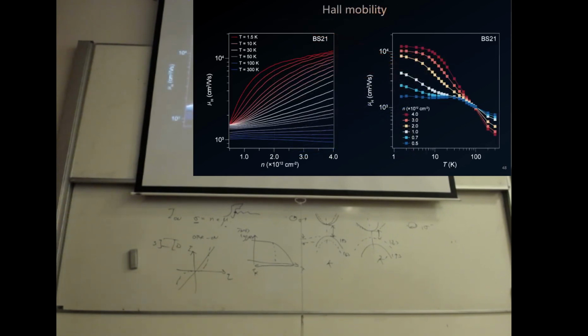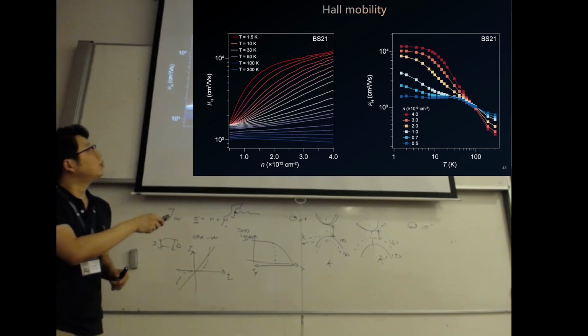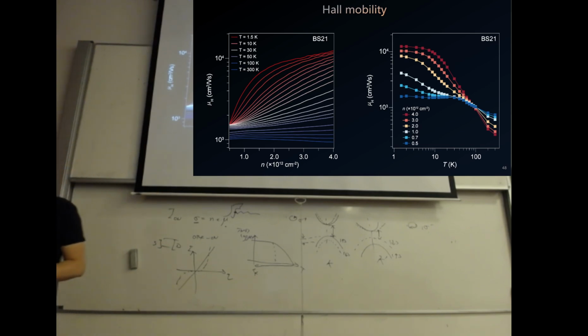And then we can have a small characterization of this Hall mobility at different temperature. This is the same thing as the left panel; the right panel is just we do line cuts along different carrier densities. Okay, and we can see that the Hall mobilities can go up to like 10 to the 4th easily in this sample. And the lowest one, which is close to the band edge, is about 1,000.